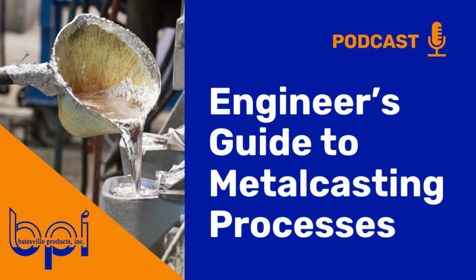That also gets you to the next topic of thin wall and the way it's drafted. In die casting, they can get away with a lot thinner walls and less draft due to the forcing of that metal into that mold. So really understanding what type of draft you need. Are you looking at straight up and down walls that you can cast in closer on a die casting, or on a permanent mold casting? You need denser walls for more of an explosion-proof type casting. Like I said, you can achieve those thinner walls on a die casting, but you won't get the metal density when compared to permanent mold and sand casting.